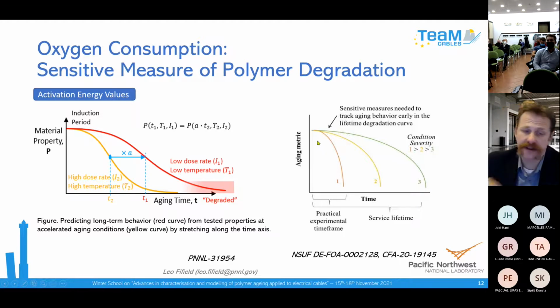Another challenge with doing accelerated aging is that if you're trying to use as mild temperatures as you can to best replicate the in-service aging, the problem is that what you're measuring, like elongation at break, might not change very rapidly until well into the aging. So in that case, we're motivated to find sensitive measures of aging, things that change predictably over time and change from early on. They don't have this kind of plateau period of aging before they finally fall off. If they change early on, you can extrapolate from early aging to long-term aging accurately, because the practical experimental time frame is short compared to a service lifetime.